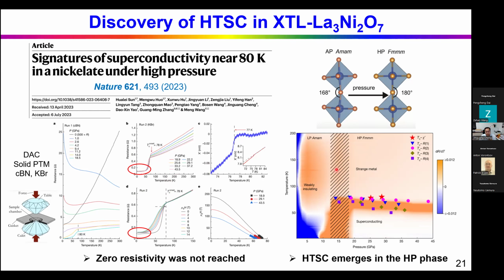In addition, there's a pressure-induced structure change from the ambient pressure phase, Amam symmetry, to a high pressure Fmmm symmetry. So the change of the structure is mainly about the nickel-oxygen-nickel bond angle. So it changed from 168 degrees to about 180. This bond angle becomes straight in this high pressure phase, and it looks like the high TC superconducting phase is directly related with the high pressure phase. But in this first report, no zero resistivity was achieved.